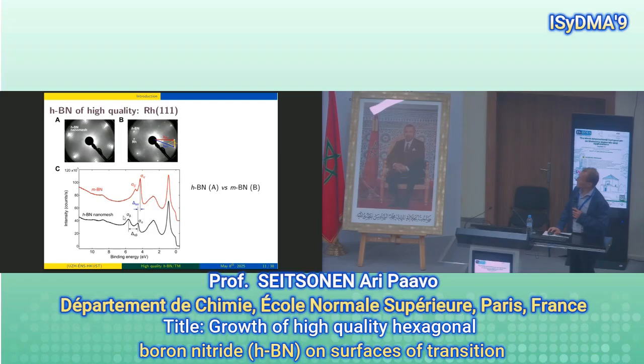Another probe for the structure is ultraviolet photoelectron spectroscopy, so just shining light and looking at the signal coming out. And this is the original hBN nanomesh. You have these two specific sigma bands at some electron volts below the Fermi energy. The Fermi energy is at 0. These are characteristic for the hBN, and they correspond to these two specific regions. I mentioned the pore, and then there are the so-called wire regions. So there are two regions where the hBN is at different height, and they give a different binding energy. And in this metastable one, MBN, the binding energy is different. So chemically, it's in a different state than in the original hBN.